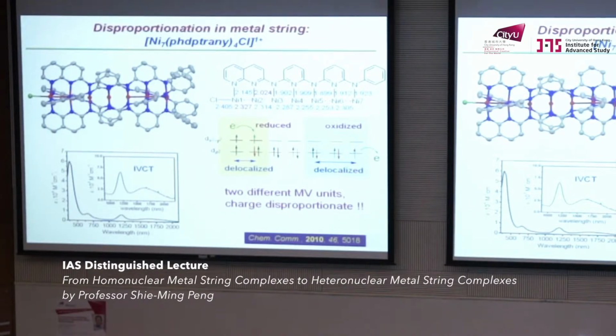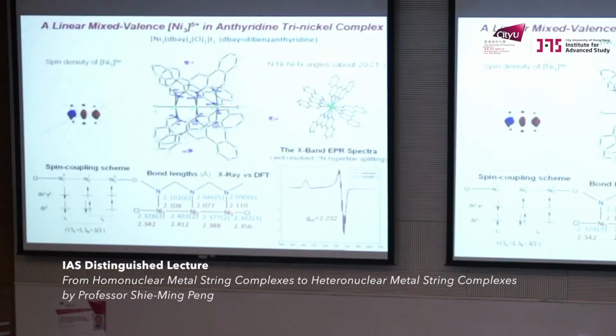This side, because more anionic, is stabilized nickel 3. So this is one example of a possible candidate for a rectifier. Nickel 1, nickel 2, nickel 3 coexist in one string because the coordination environments are different. And recently, we even used the dibenzanthyridine to get the nickel metal complex.